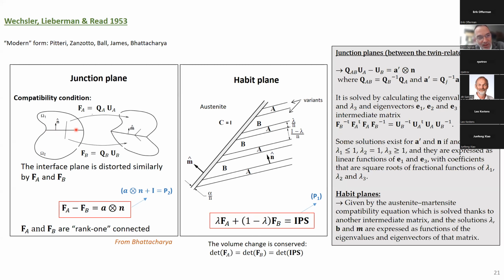It means that what happens at the interface should be distorted similarly by this distortion matrix and by this distortion matrix, okay? Mathematically, if you want this condition of compatibility at the interface, which is a junction plane here, you can write this compatibility by this equation. You take the first distortion minus the second distortion, and it should have this form. This form is more or less the form of a simple shear minus identity. They call this relationship rank-1 connected: the two matrices are rank-1 connected. With this equation, you can find the junction plane.